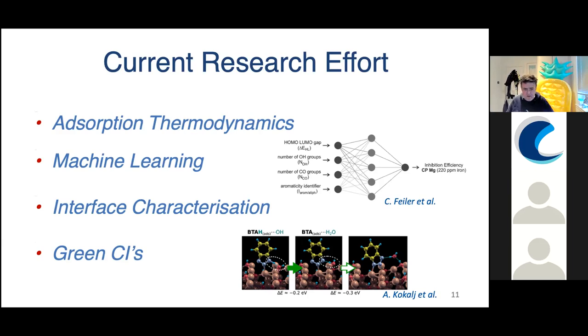There's also interface characterization, and that's what we do. It's a bottom-up approach, trying to understand what's happening at the molecular scale. For instance, this is atomic scale calculations done by Anton Kokalj from Slovenia, where he's looking at the interaction of benzotriazole with a surface of copper in this case, and looking at how this inhibitor molecule, which is well known as an inhibitor, interacts with the surface. There's also experimental work, and that's what I'm going to talk about in a moment. Finally, there's a big push for green corrosion inhibitors. And if I have time, I'm going to make a few comments on that at the end.